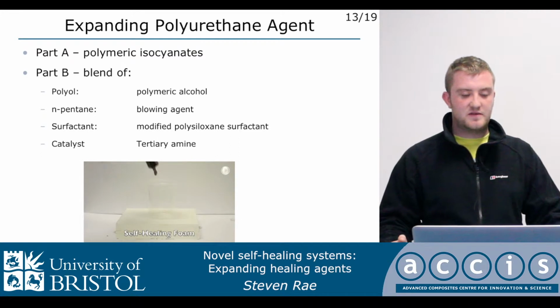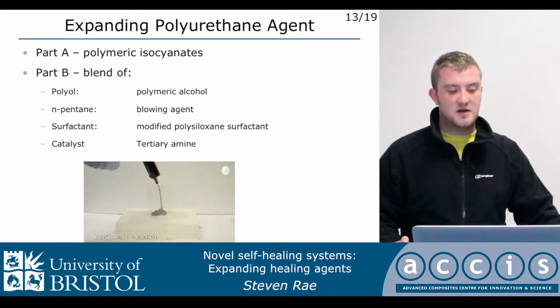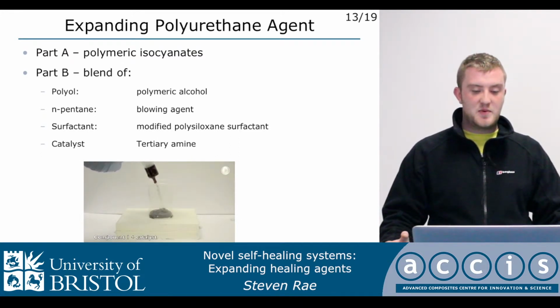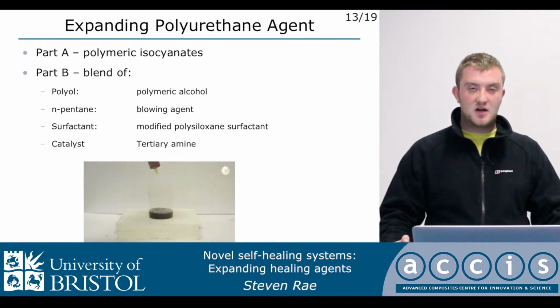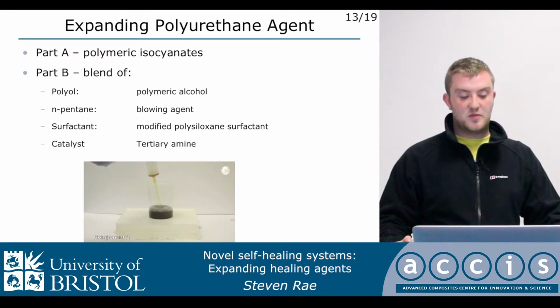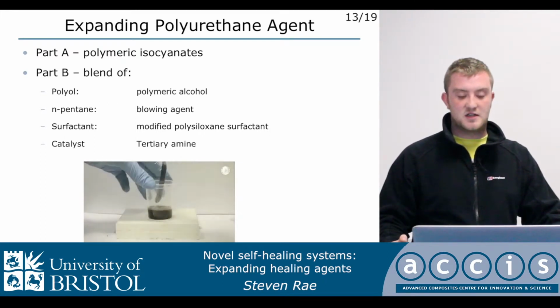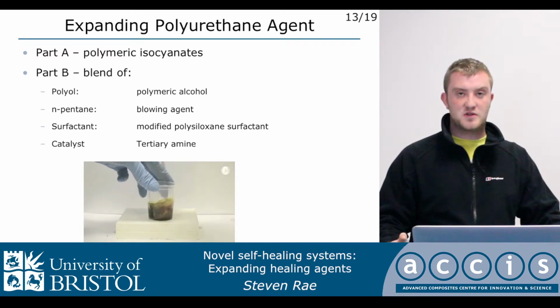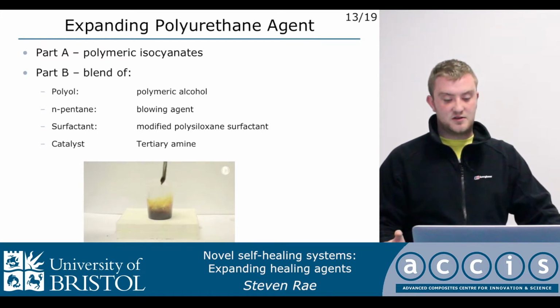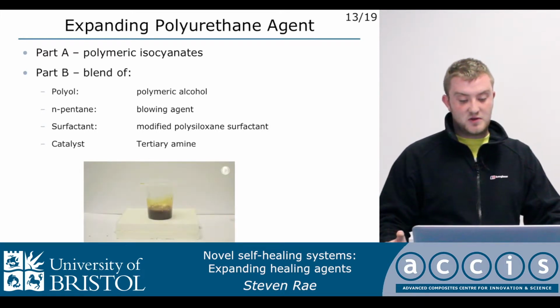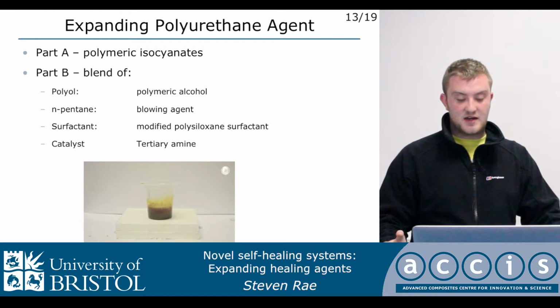The second healing system that I've been developing is based on a polyurethane system. Again, two parts. Part A being a polymeric isocyanate, and part B being a blend of polyol, which reacts with the isocyanate to give you the polymer itself, a blowing agent in there which we can evaporate to increase the expansion, a surfactant which helps bind everything together and keep it stable, and of course a catalyst to get the reaction to occur. As you can see in the video, when the two parts are mixed, rapidly we get an expansion, usually in less than 10 seconds, and quite a significant expansion in that.